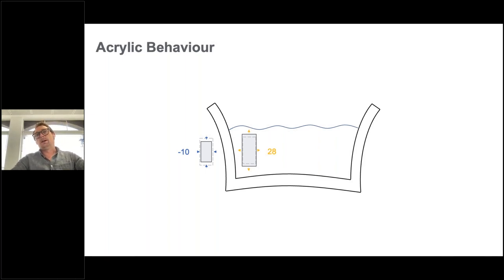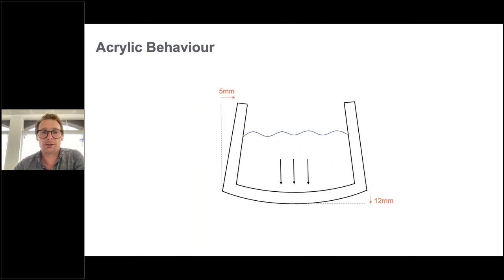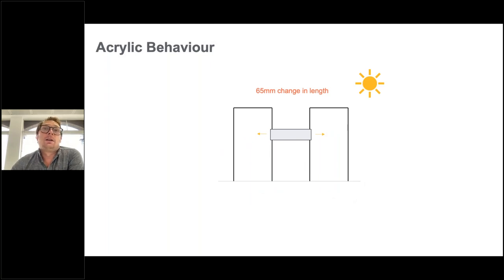So we have this thermal load case where we're getting this warped shape. So this is a cross section. But from a water loading point of view, the walls are trying to come inwards. We also have the change in length. So acrylic has a much higher thermal rate of change with regards to glass and other materials. And so we have a 65 millimeter change in length, which is pretty substantial in building terms.